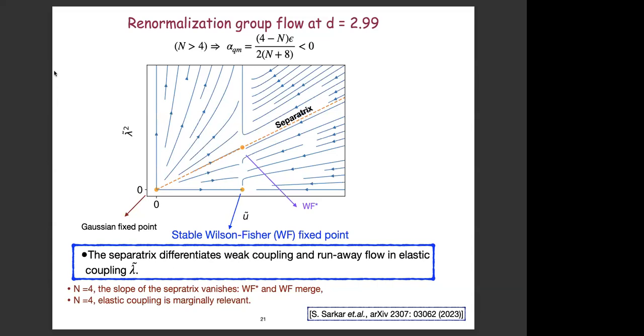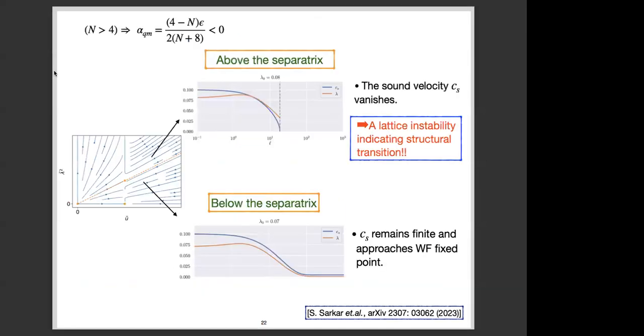And you said the slope of this line depends on the value of n? Yeah, because I haven't shown it here, but if you consider a particular parameter range, like CS over C is very small, then the slope is sort of like n minus 4 over n. So if n is close to 4, this line basically goes towards the x-axis. So if your n is less than 4, you always have a first order transition with the massive value of n. Whereas if it is above 4, then we will see what's happening in this region, because these two flows are quite different here. Okay, so these plots are not that great.